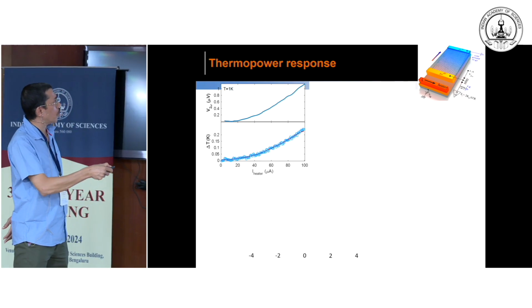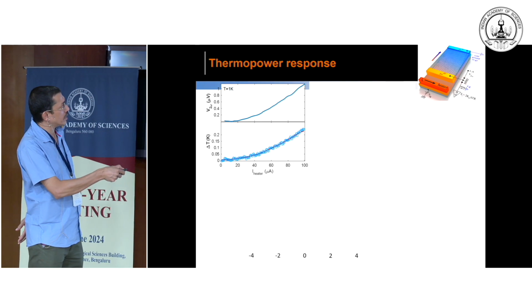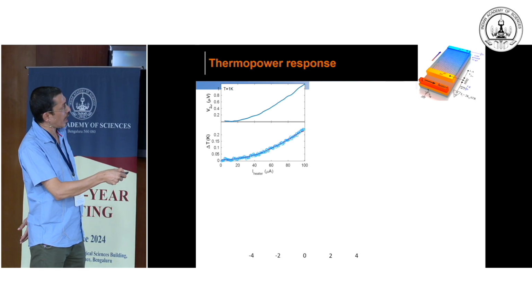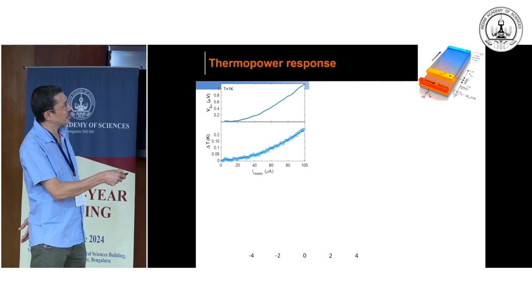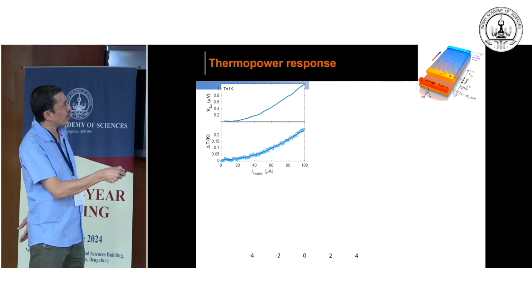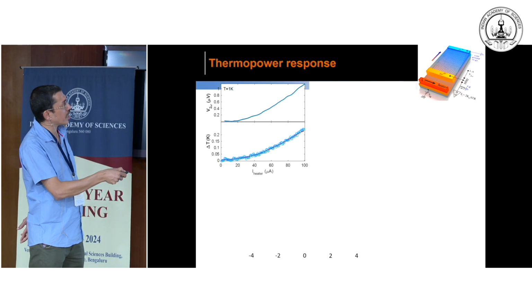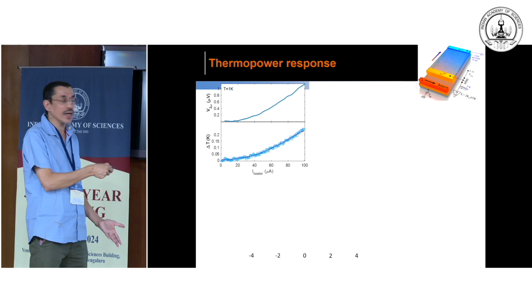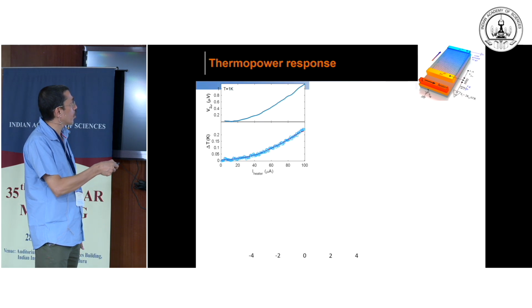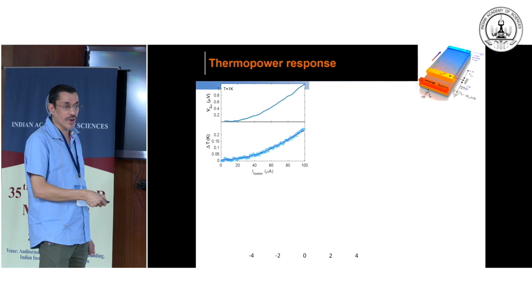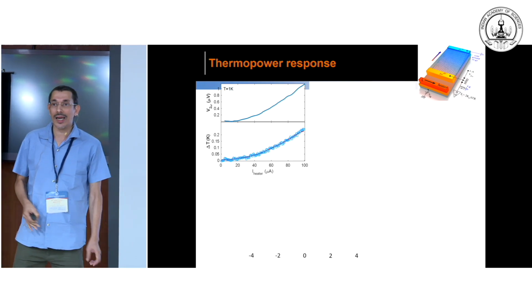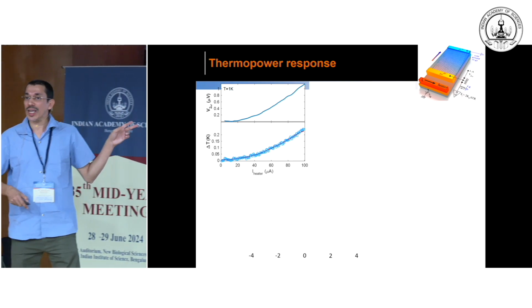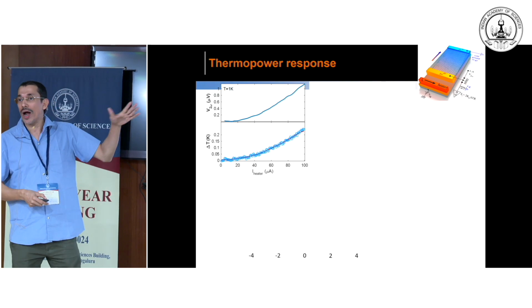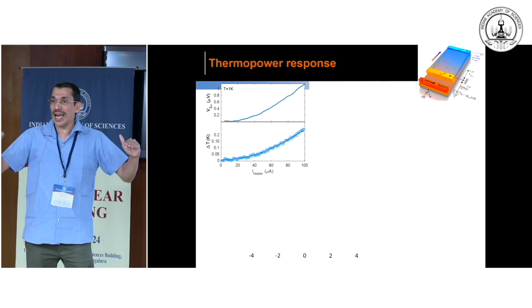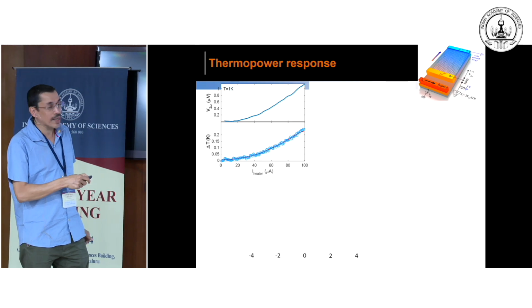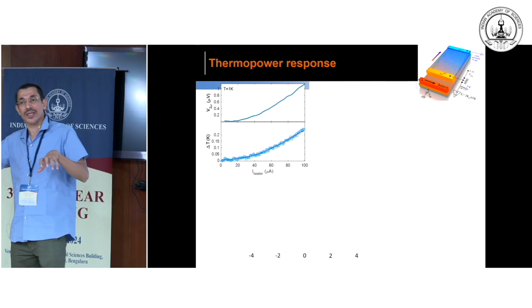As I told you, there is a heater connection here. We pass a current along the heater, and that generates a temperature gradient across the sample. So you have a hot end and a cold end, and we measure the thermoelectric voltage. This is a well-known technique called the V2 omega technique. We also measure the temperature difference because this experiment has to be done in a linear regime, and I'm talking about very low temperature, even 100 millikelvin to 1 Kelvin. So the delta T has to be extremely small. We have developed a technique called Johnson noise thermometry to measure the temperature.